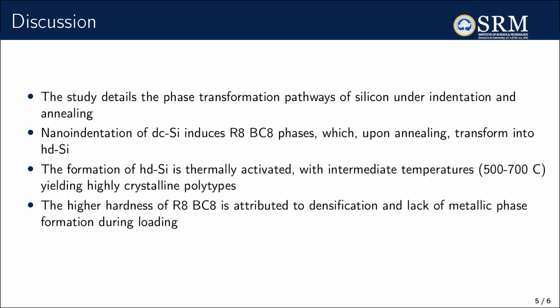The study details the phase transformation pathways of silicon under indentation and annealing. Nano-indentation of DCSi induces R8/BC8 phases, which upon annealing transform into HDSi. The formation of HDSi is thermally activated, with intermediate temperatures of 500-700 °C yielding highly crystalline polytypes. The higher hardness of R8/BC8 is attributed to densification and lack of metallic phase formation during loading.